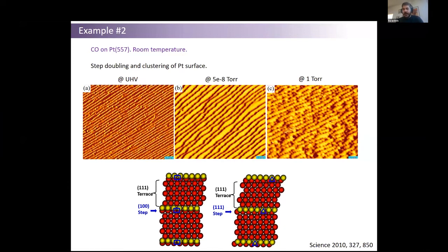Now, this is already interesting by itself. Actually, the stability of the step structures is already interesting by itself, but we see that there is a change. They are a bit destabilized, basically, in the presence of gases. Now, when you go to even higher pressures, you see that they're completely unstable. They break up into clusters, in the form of, it's not well resolved in these images, triangular clusters. In studies later on, people actually show these triangles, both in the presence of gases and in the presence of liquids. So now it's the first time that a surface was shown to break up into clusters in the presence of gases.